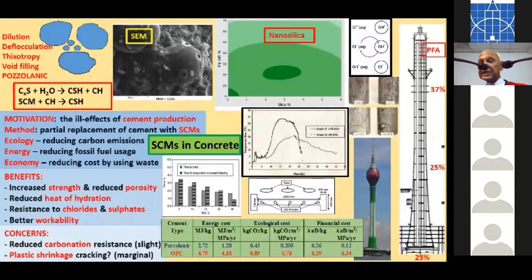So when the Lotus Tower was being constructed, the base of this foundation was 2.5 to 3 meters thick. And it was a no-brainer that we would have to use PFA, 25% PFA. That was the mix that was available in order to concrete this so that the temperatures could be kept below 70 degrees or whatever number it was at that time. So there is increased strength, reduced heat of hydration, then resistance to chlorides and sulfates as well.